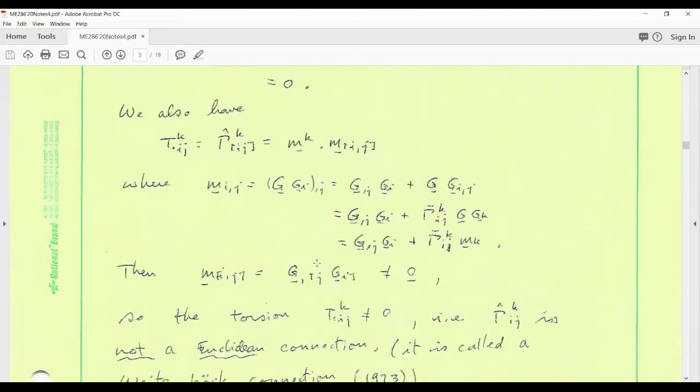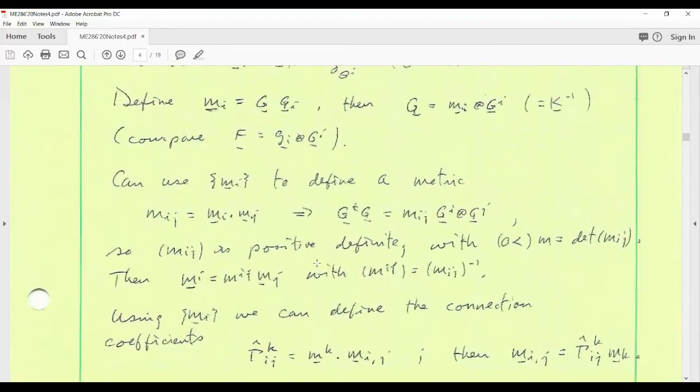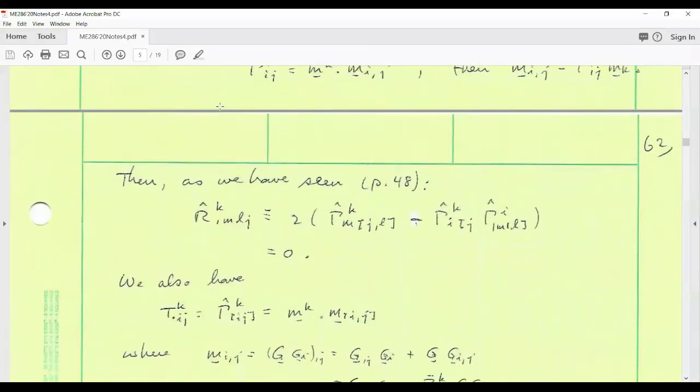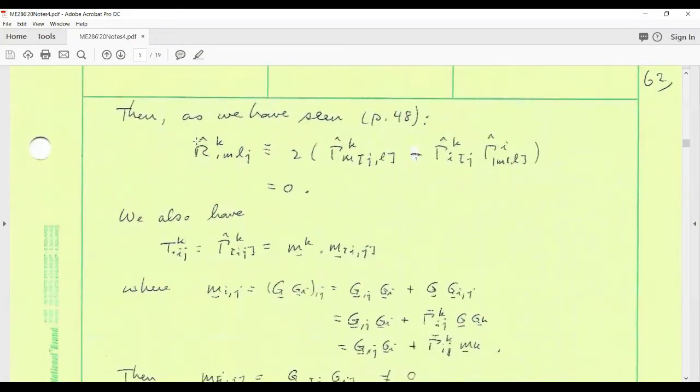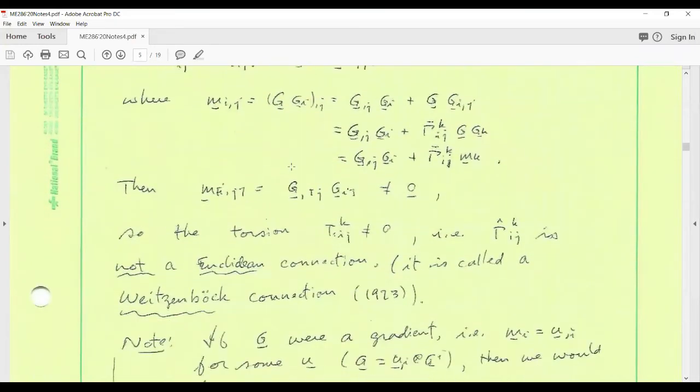these vectors induced by mapping the referential vectors into the so-called intermediate state by using the plastic deformation can be associated with a non-Euclidean geometry. It's flat, 0 Riemann tensor, but it has torsion. Okay? So therefore, this manifold we've now constructed is not Euclidean.